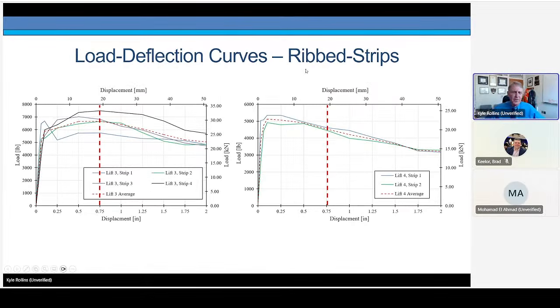These are load deflection curves for the rib strips. You can see that they tend to reach a peak at fairly small displacements, in some cases a tenth of an inch or maybe a quarter of an inch, and then there's a tendency for this to drop off. When that would happen, there was a big popping sound. We suspect maybe this is where we're losing some of our cohesion, and maybe the friction is taking over. We picked our resistance as the maximum value within 0.75 inch of displacement. So we would have picked this value here. We'd have picked this value here for the rib strips.